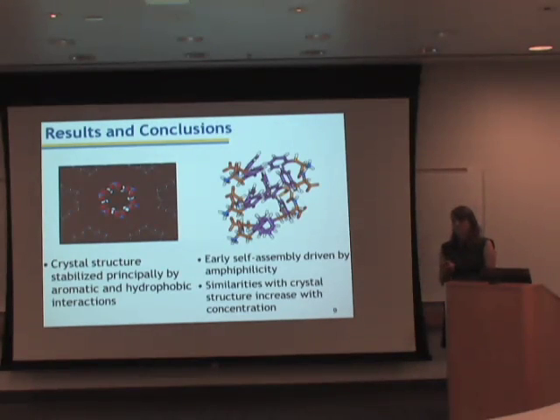We've learned many valuable things from our simulations so far. Firstly, we have found that the crystal structure shows the most amount of interaction between hydrophobic groups, leading us to believe that it is stabilized principally by aromatic and hydrophobic interactions. From our simulations of free-floating peptides, we have learned that the early self-assembly of diphenylalanine is driven by the amphiphilicity of the peptide.